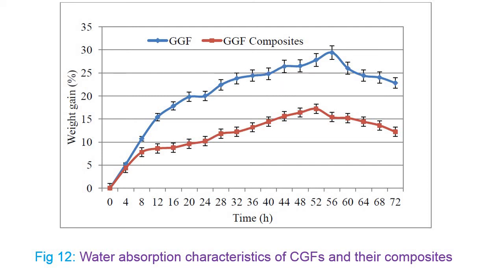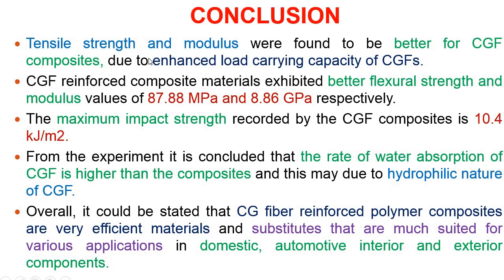The reason behind this is that natural fiber generally has a hydrophilic nature. Due to the hydrophilic nature, the Calotropis gigantea fiber has the tendency to absorb many water molecules when compared with the Calotropis gigantea fiber composites. We took 72 hours in total, and we recorded a reading periodically on a 4-hour basis. We used a water absorption tester machine. And then finally we come to the conclusion.